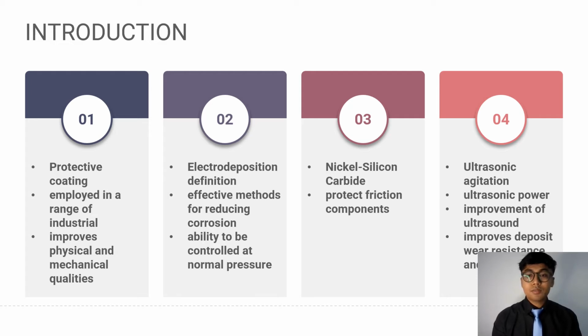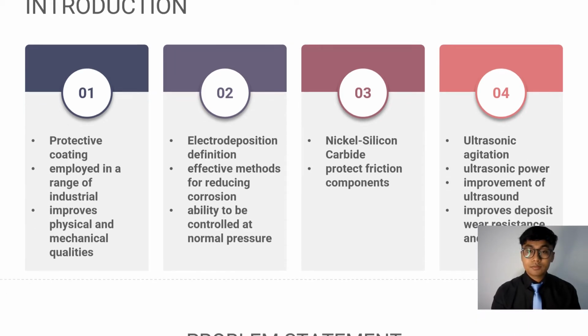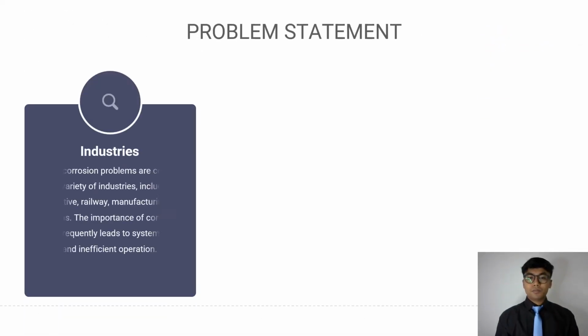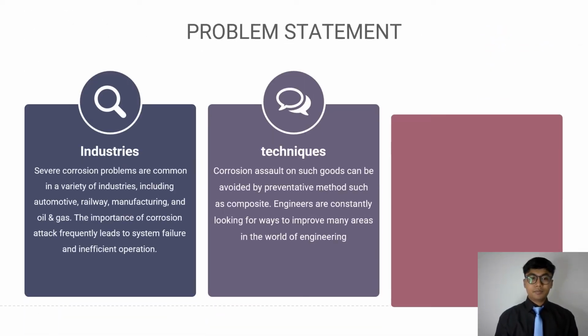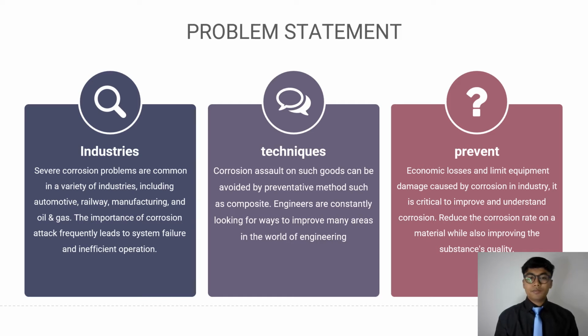electrodepositions. Ultrasonic power substantially impact the microstructure, phase structure, surface morphology, and other aspects of the composite produced. Ultrasound has been shown to improve both the electrodeposition process and the properties of nickel silicon carbide when used in electrochemical operations. For the problem statements, the most typical concern with the materials have been found as wear and corrosions.